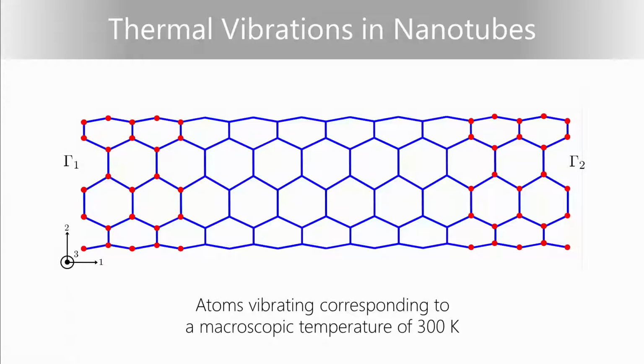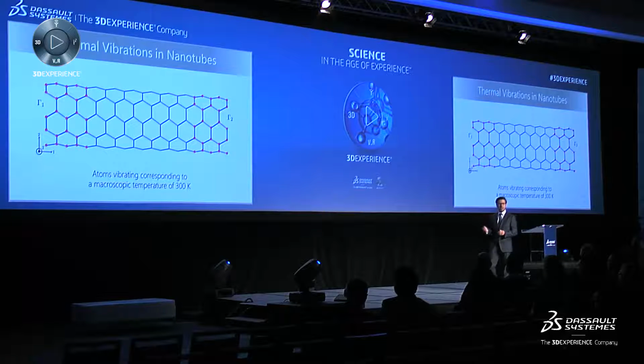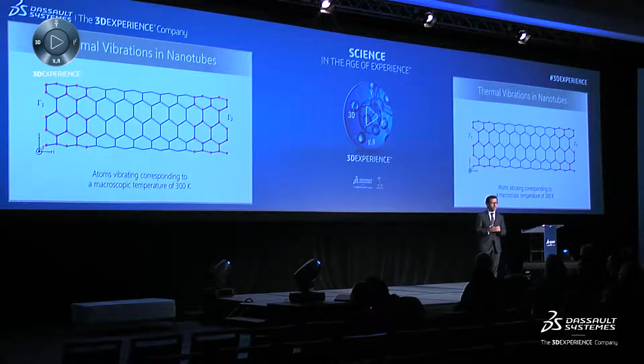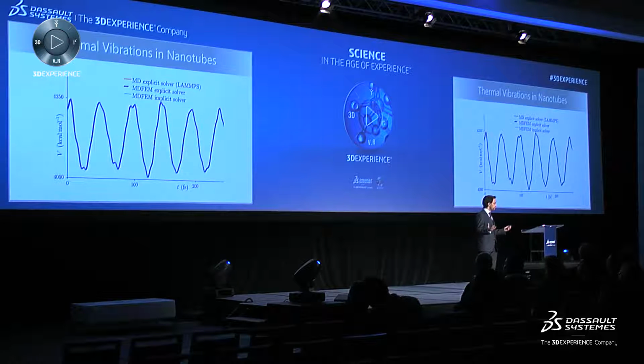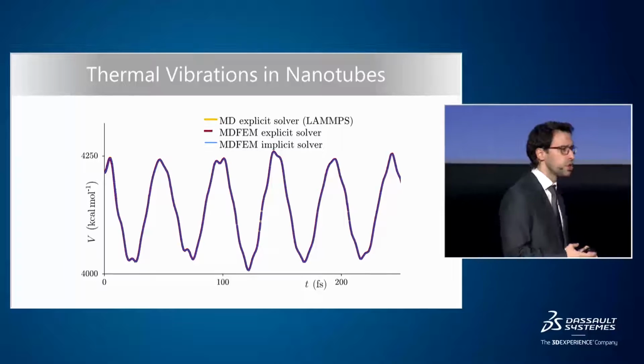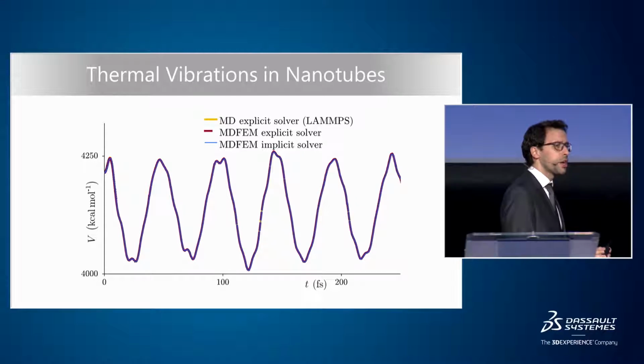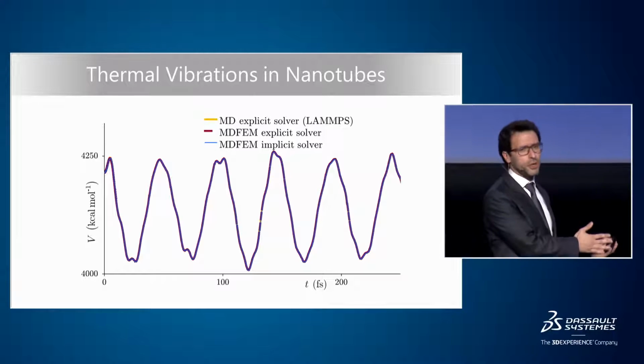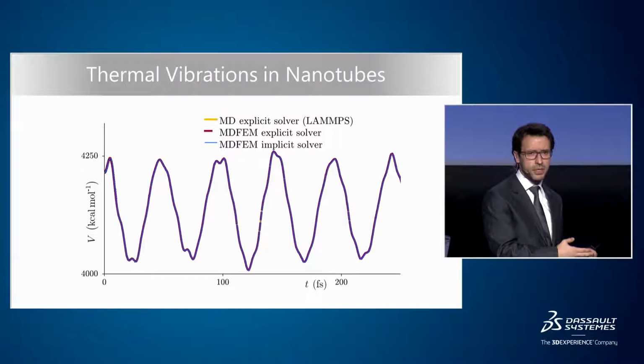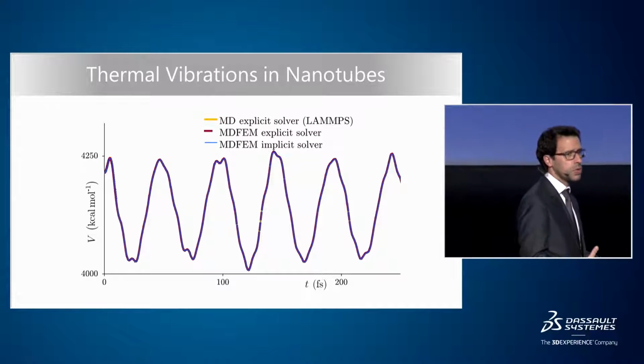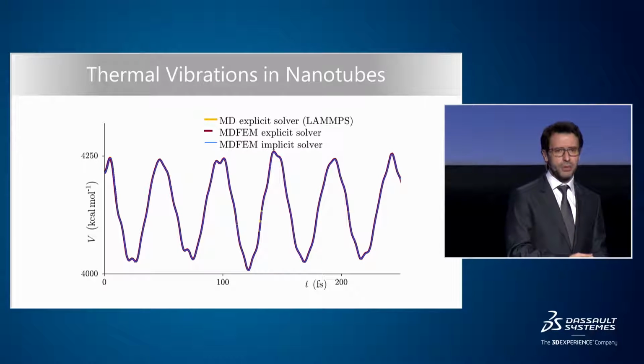I'll start with a validation example. This is a carbon nanotube at 300 degrees Kelvin, and it's vibrating. And if we compare our solution in Abaqus, both with an implicit and an explicit solver, we get exactly the same solution as we get with LAMMPS. So we are not creating an approximate version of molecular dynamics inside Abaqus. We've created actually an exact solution of what you can get in molecular dynamics, but inside Abaqus.